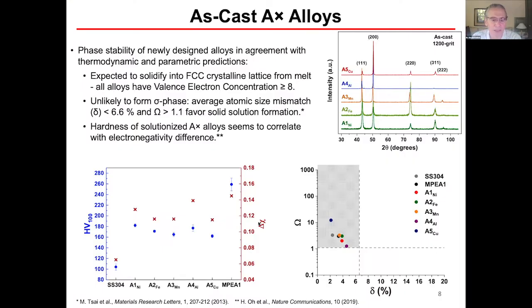So these are the as cast. You asked, did we measure the hardness in the solutionized alloy? Right. So the solutionizing decreases the hardness a little bit, but again the phase formation results in a strong increase in the hardness.